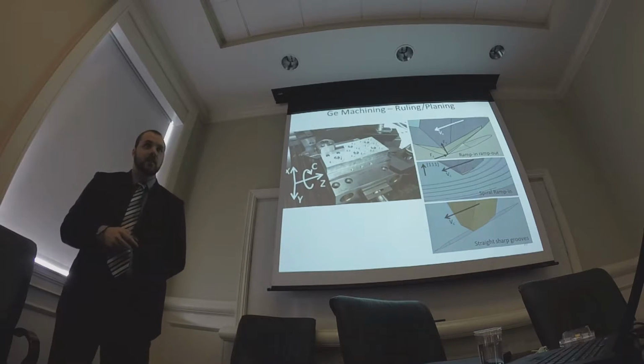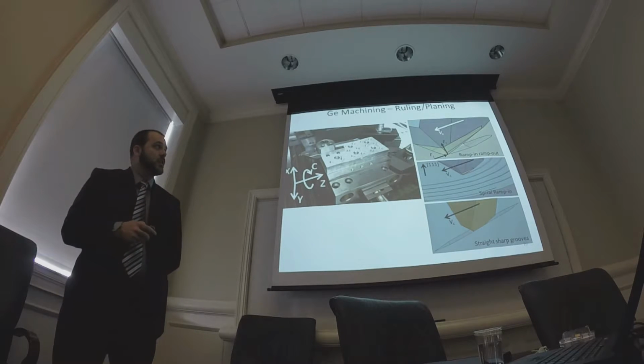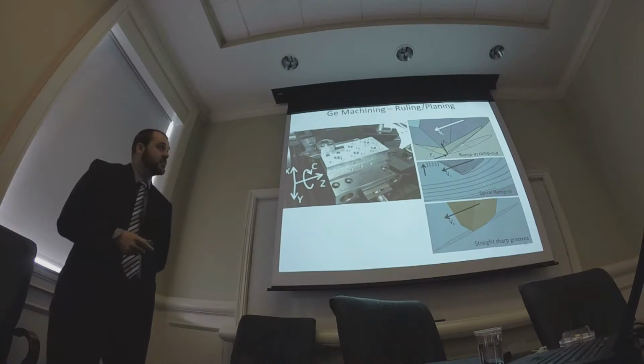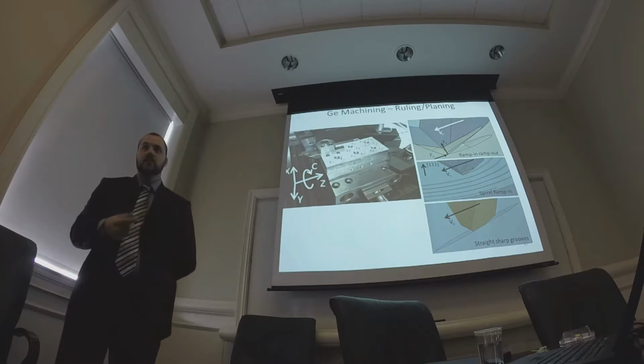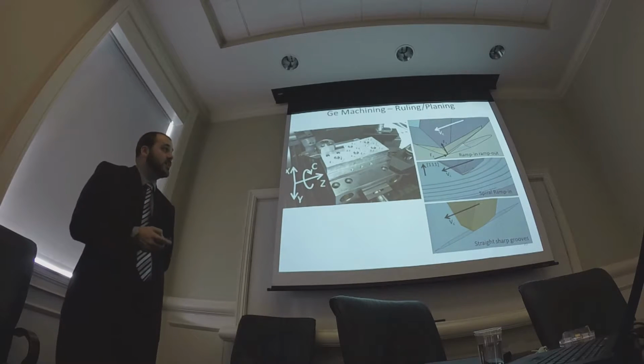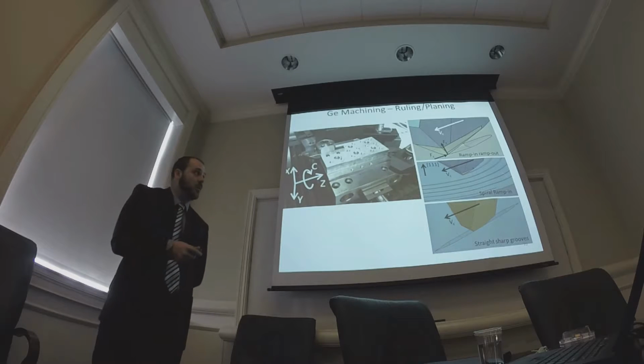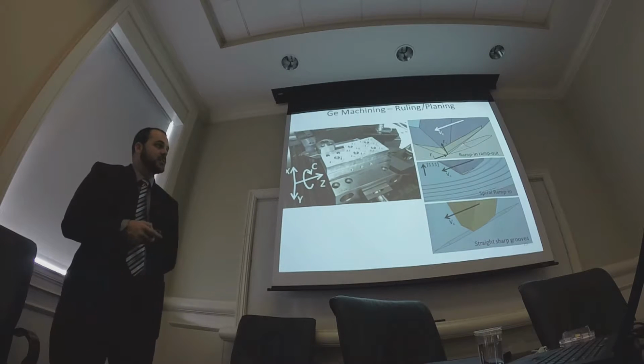Same Kistler dynamometer setup. We've got a round nose tool used for ramp in, ramp out tests while taking force measurements. This allowed us to see where fracture occurred on the surface after the test. Same with the spiral ramp in, all non-overlapping cuts.